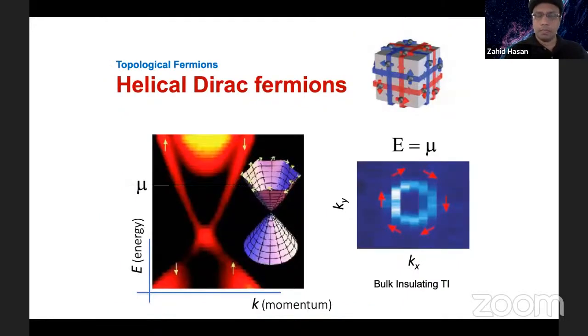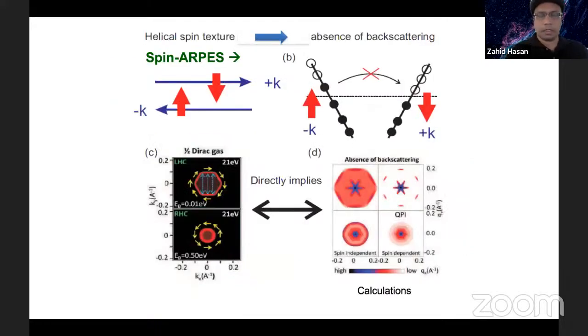Okay, so the simplest scenario that is emerging is that if you take a 3D topological insulator and place the Fermi level inside the bulk gap, then you will have a scenario like this. In real space, it will be like this. Here you have an insulating bulk and a conducting surface, but conducting in a very special way, in that the surface conduction is through helical Dirac fermions. Okay, so what is the transport consequence of all of that?